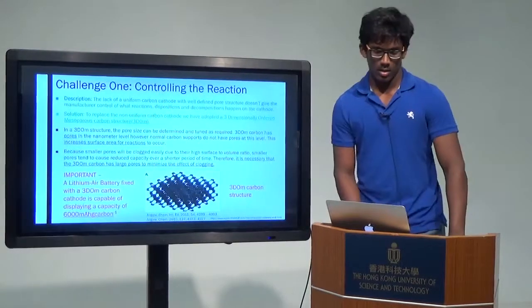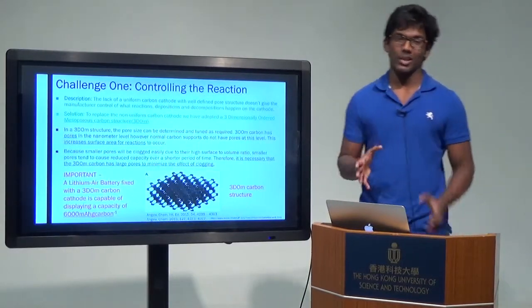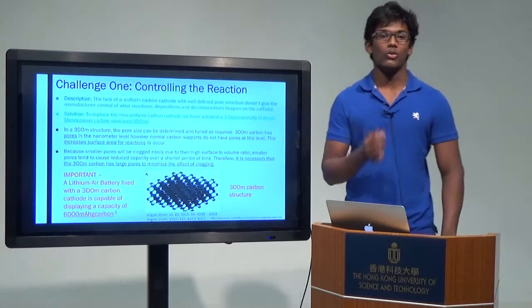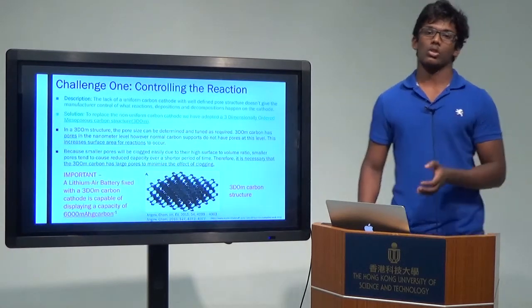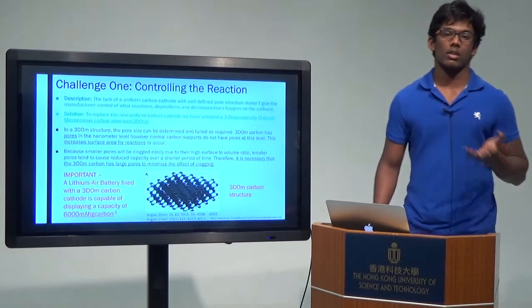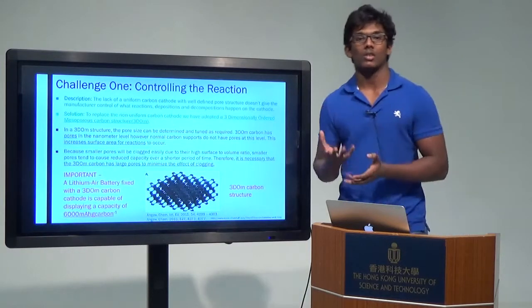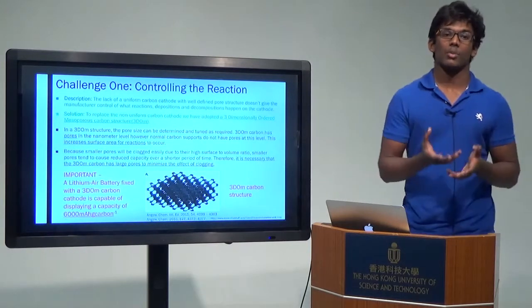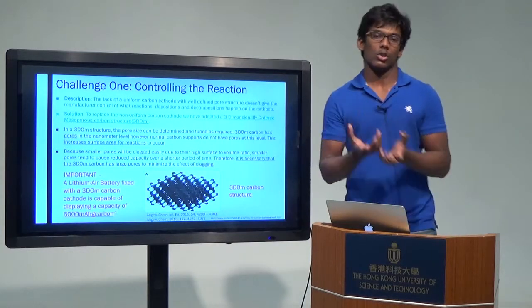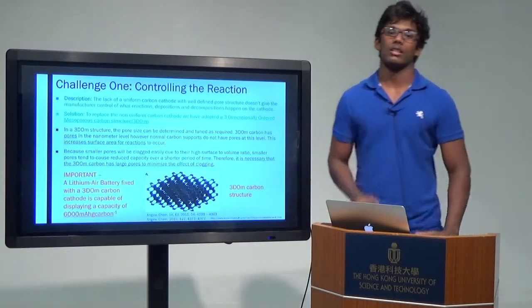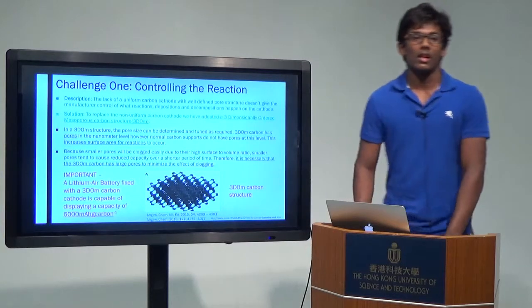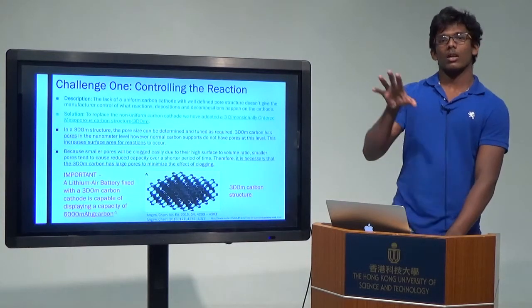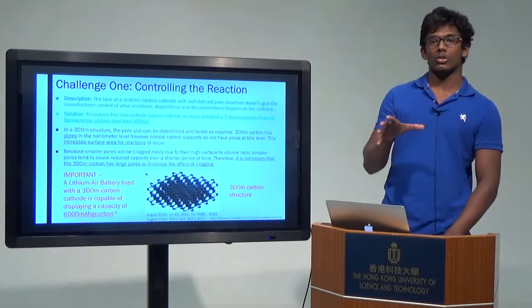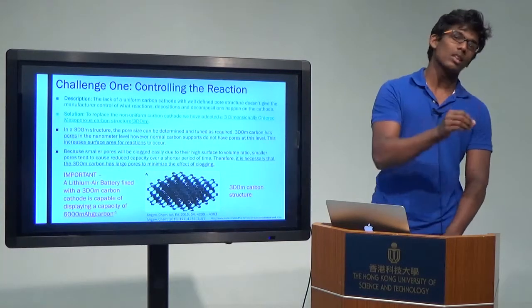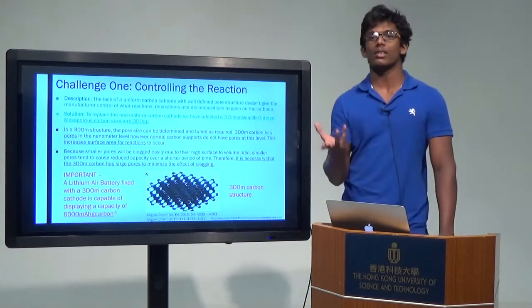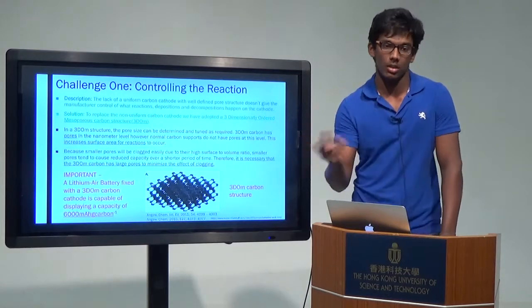per kilogram. The first challenge with the lithium-air battery is the lack of a uniform carbon cathode with well-defined pore structure, which doesn't give the manufacturer control of what reactions, depositions, and decompositions happen on the cathode. To solve this, we have adopted a three-dimensionally ordered mesoporous carbon structure. A 3DOM carbon has well-defined pores and good uniformity at the nanometer scale level. So we are increasing the surface area, increasing the rate of the reaction.